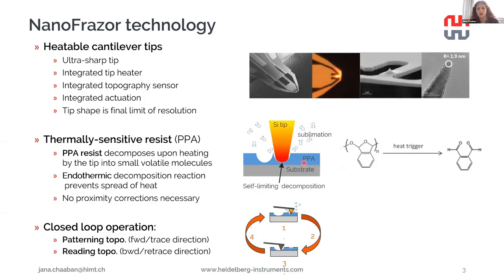We can use such a technique to write nanometer resolution features. In this case, the tip shape itself, which you see here, gives the final resolution limit. In our case, because we employ ultra-sharp silicon tips, this is the equivalent of about 10 nanometer resolution in the lateral direction and about 1 nanometer in the vertical direction. What's very important here as well is that no proximity corrections are required.